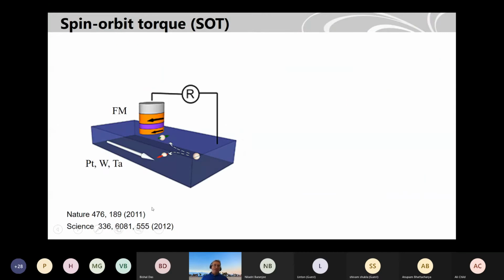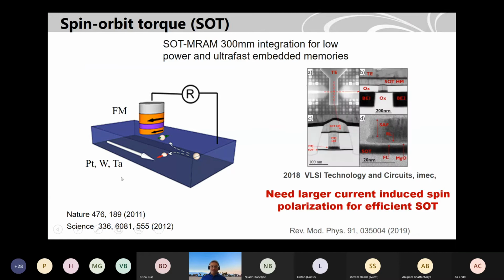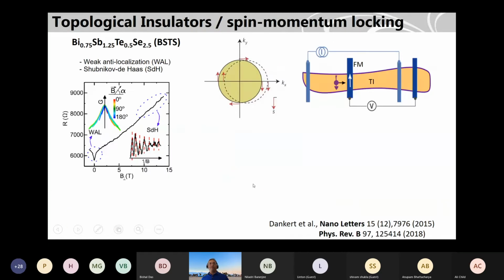And as I told you in the last lecture, people use platinum, tungsten, tantalum, heavy elements, and the industry is trying to develop spin orbit magnetic random access memory using these metals. But they are looking for metals with high spin polarization. And this is the limit which actually prohibits industrial application. Maybe it's one of the reasons that you need a little bit higher current to create more spin polarization. But if you use a topological material instead of these conventional metals, you can create larger spin polarization, and that may help to develop these technologies.